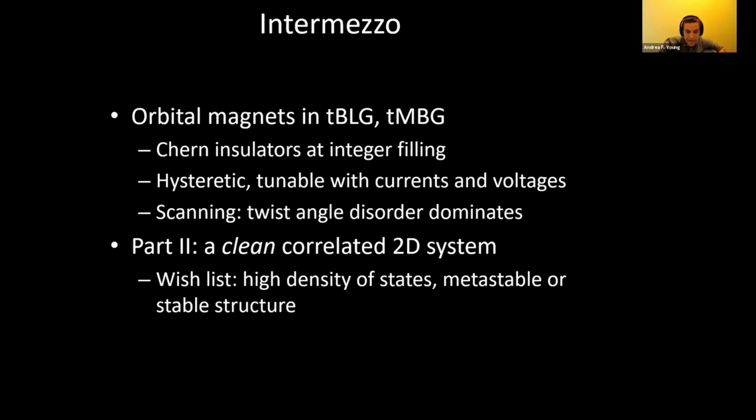mesoscale disorder. It's not self-averaging disorder. It's not something that you can think about as being uniform in any way. They're really things that are non-uniform on the scale of a reasonable fraction of the scale of the device. So 100 or 200 nanometer domains at best, and a lot of this mesoscopic scale disorder is very annoying. It really impacts reproducibility in a way that even microscopic disorder would not.